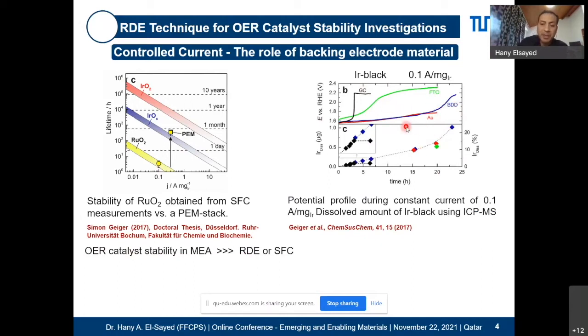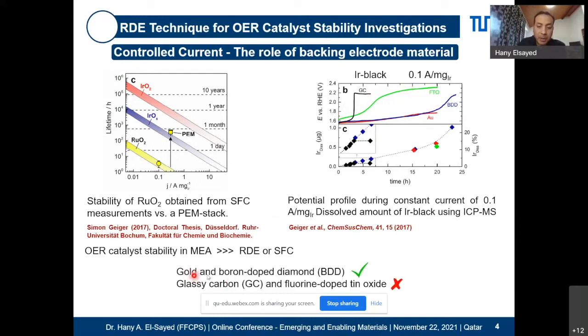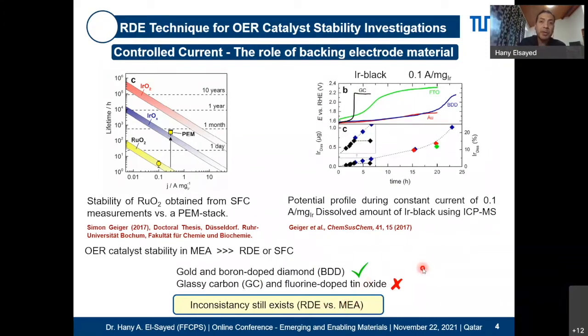But even so, that's all RDE testing. So this is the effect of substrate. They can recommend this and exclude, of course, glassy carbon. But the issue is that the inconsistency still exists, which is RDE versus MEA. In MEA, the catalyst can last for hundreds of hours, but in RDE, it can only last for 2-3 hours. So where does this come from?